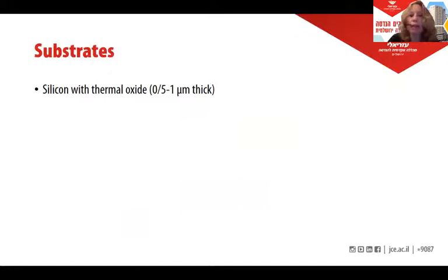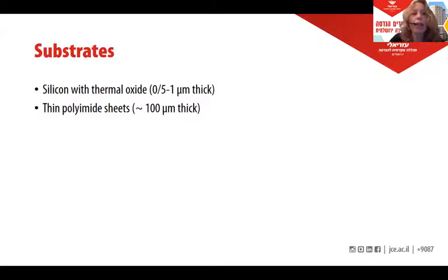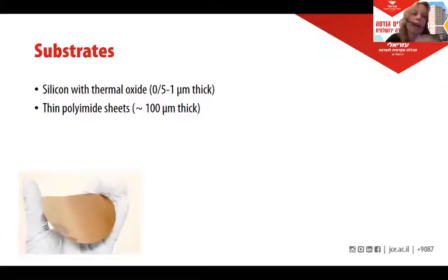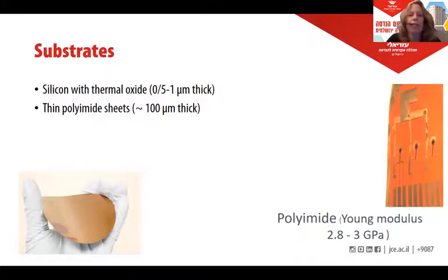We deposited the ZnO on two substrates. First, silicon. We all know what a silicon looks like, about a half or one micron thick silicon substrate. And the other one, in order to be flexible, we deposited the ZnO on polyimide sheets. Polyimide about 100 micron thickness. This is how a polyimide sheet or wafer looks like. We have a lot of experience in Yossi Shacham's lab in depositing on polyimide on flexible substrates.